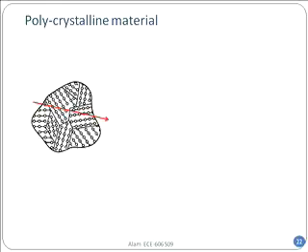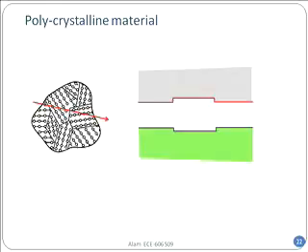Let's say it is going in various directions. Now you know that the band gap in different directions is different. Do you know that in crystalline material? Along the L direction and along the X direction, the band gaps are not the same, are they? So on its route, going from one side to another, the electron will see a variable band gap as it is going through.